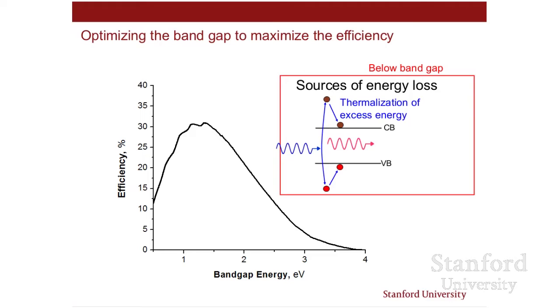With a high band gap, we get a high voltage, but we get a low current because we get one charge carrier per photon absorbed. And so on the curve of efficiency versus band gap, you see that it starts low, rises to a peak, and then it falls. And from this, we see that the ideal band gap is about 1.4 electron volts. And with one semiconductor, the highest efficiency you can get with the sun is about 31%.